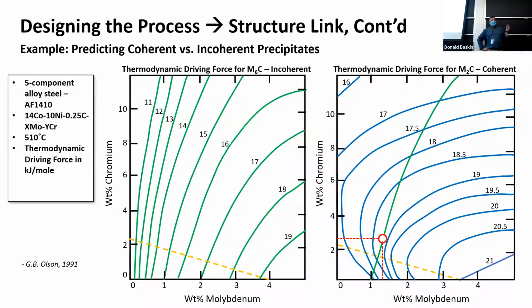So you guys see where this is very, very powerful all of a sudden? You look for phases that have a high driving force. You look for the alloy composition and the temperatures that maximize the driving force to precipitate out these little particles. Because you know that if you get a bunch of these things, little tiny pieces all over the place, you're going to have the biggest increase in strength. So here we are again, we're designing the material. We're picking temperatures, we're picking compositions that maximize this thermodynamic driving force to form M2C carbides over, say, M6C carbides, right?